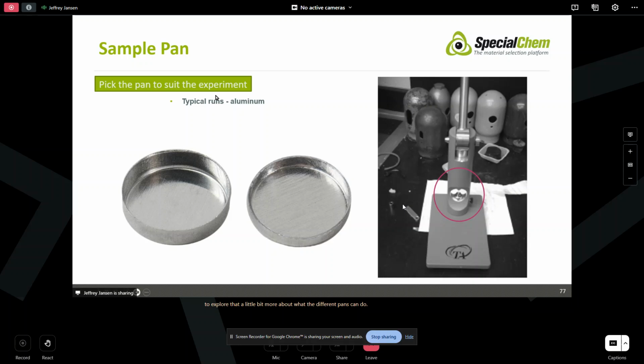So a lot of our experiments are run in just simply what's called a crimped pan. Now, you can do this with just a crimped, or you can do this in hermetic. But the two pans, the bottom and the top, our sample goes inside of here. The lid goes on top of here. It goes into this crimping device, and that crimps the pan, closes it shut. And that's how most of the samples that we run are run. Now, again, that's an aluminum pan.